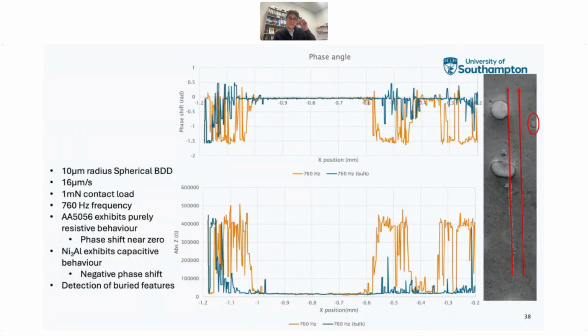Finally, we tried this on the original material we looked at, the metal matrix composite that we had, and so we've made two traces here in the red lines. So we've traced twice. We've done some background work in other areas of the sample, probing it using these frequency sweeps, and decided to settle on a particular frequency. In this case, it was 760 hertz, and then made a double trace across these